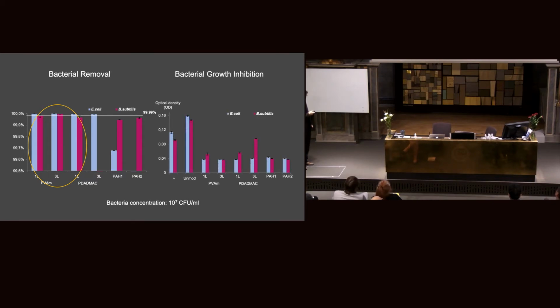We also checked bacterial growth inhibition, and found that the 3-layer PVAm still stands at the top with very good results. It can inhibit the growth of both E. coli and Bacillus subtilis.